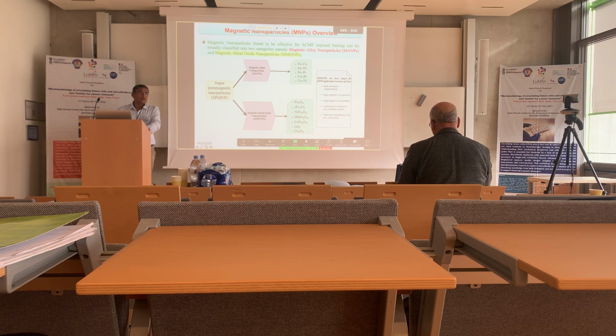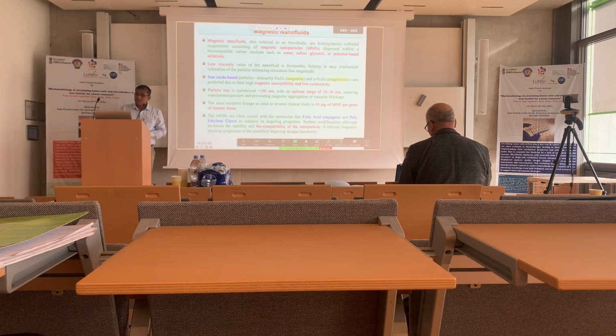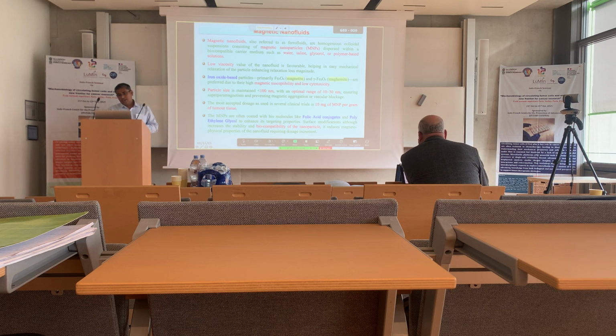Under different available tests and also some experimental tests, we found that magnetic metal oxide based nanoparticles respond quite well for magnetic fluid hyperthermia. So we have picked up that category of material, particularly magnetite and hematite. These 2 types of particles are good for magnetic fluid hyperthermia, and particularly a nanoparticle size less than 100 nanometer, with an optimal range of about 10 to 30 nanometer.